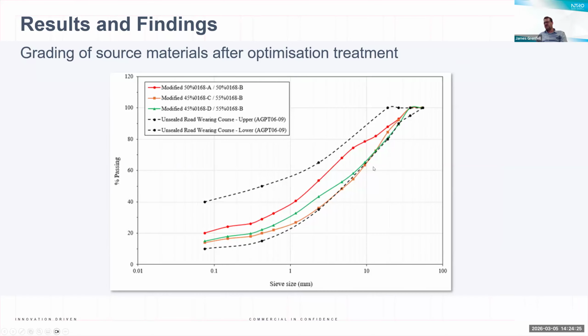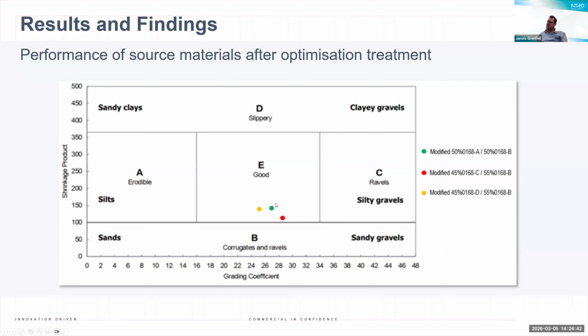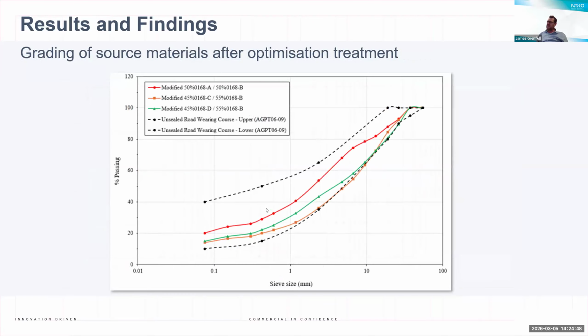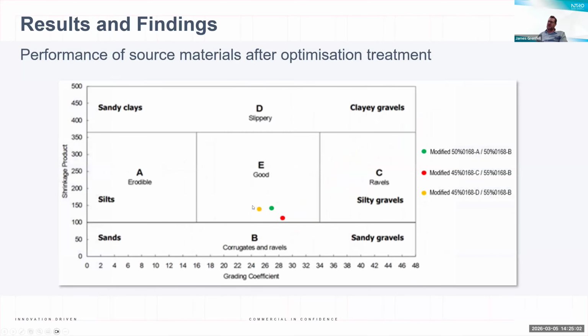What could we do in terms of improving the gradations? So again, this is now looking at some of those materials and blending them to improve their gradation and getting them to fit much better within the grading envelope. And what does that now mean in terms of where they sit on the performance chart? So by undertaking this blending, so blending, say, 50% A with 50% B, 45% C with 55% B, and 45% D with 55% B, we've now been able to bring all of the materials up into the good area within the chart.